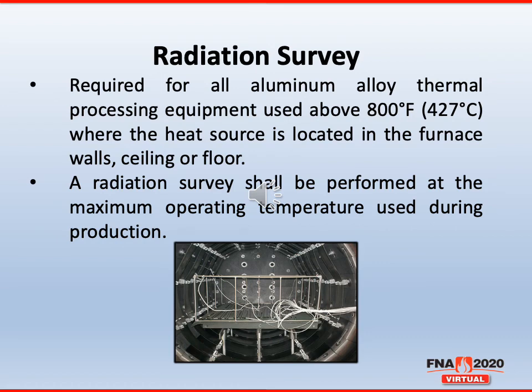So the change for the radiation test survey: prior to the release of the specifications in AMS 2750E and before, it only required that the radiation test surveys be performed on all solution heat treating of aluminum alloys. And the wording has changed. Now it's required for all aluminum alloy thermal processing used above 800 degrees, where the heat source is located in the furnace walls, ceiling, or floor.